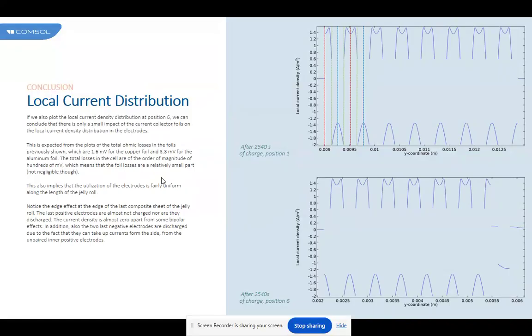Conclusion, local current distribution. If we also plot the local current density distribution at position 6, we can conclude that there is only a small impact of the current collector foils on the local current density distribution in the electrodes. This is expected from the plots of the total ohmic losses in the foils previously shown, which are 1.6 millivolt for the copper foil and 3.8 millivolt for the aluminum foil. The total losses in the cells are of the order of magnitude of a hundred millivolt, which means that the foil losses are a relatively small part, though not negligible.